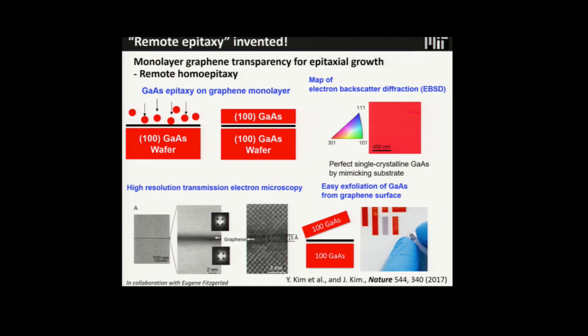Then, in order to double confirm, we transfer the polycrystalline graphene on 100 gallium arsenide. Polycrystalline graphene is given from Professor Jing Kong. We transfer, we grow, then still single crystalline. We double, triple confirmed. Your underlying substrate become your seed layer. And also, we did some TEM to see the atomic alignment through graphene. As you can see, there is a monolayer graphene, but gallium arsenide aligned to the underlying substrate through graphene.